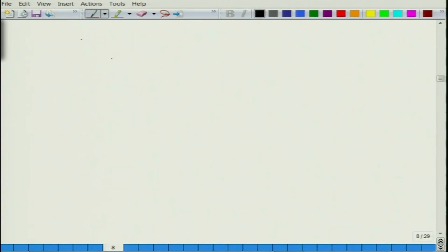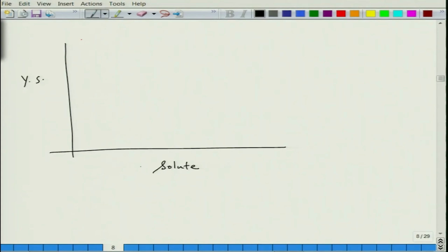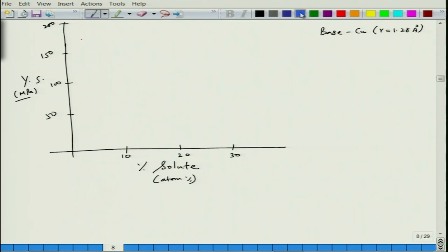So basically there are people who have studied this. If you plot, for example, yield strength as a function of percentage solute addition, let us say this is 10, 20 and 30, and this is atom percent. And let us say this is 50, 100, 150 and 200, in MPa, megapascal. Here the base matrix is copper, and copper has a radius of 1.28 angstrom. In case of copper, zinc creates some strengthening up to about 30%, and zinc is about 1.31 angstrom.